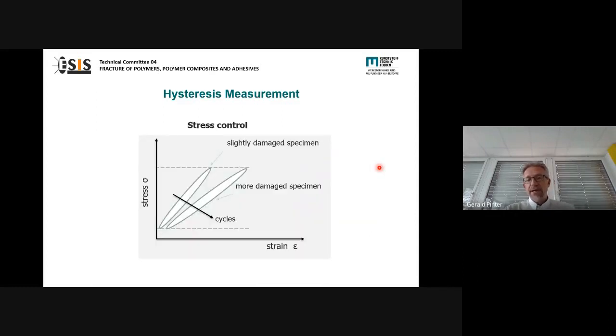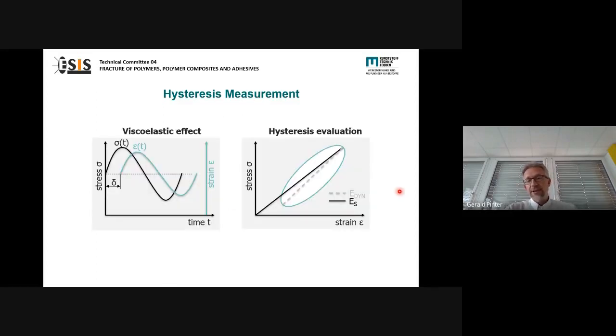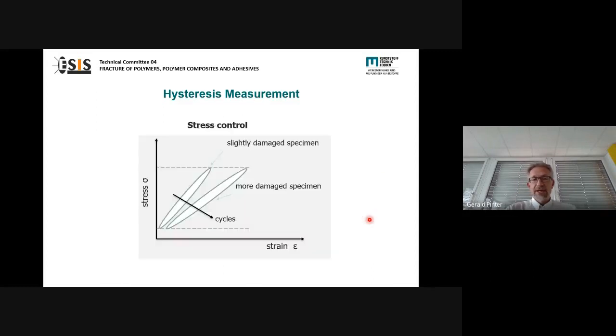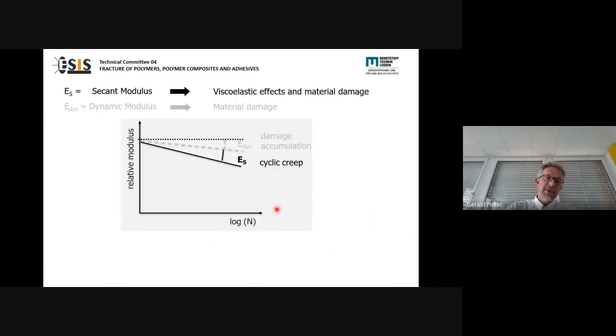And if you compare now the hysteresis as a function of the cycle number, you typically will see that the hysteresis loops change. On the one hand, they can shift to the right. This is typically a result of viscoelasticity and creep effects. Also the slope of the hysteresis will change, and this typically is the result of damage that happens in the material, in the polymer. And now if you calculate the moduli, the secant modulus and the dynamic modulus, you typically can get such a diagram. You see here the relative modulus as a function of the cycle number.